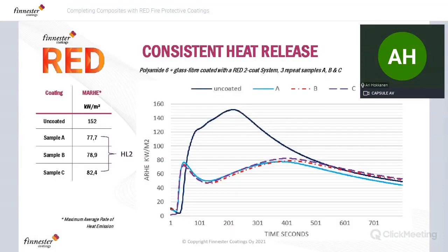And then one further graph we have is what we were talking about, consistency. A big problem particularly in the railway standards world, the EN 45545, is that you have a black and white threshold number that you have to get below to get to a certain classification. In this case, it's called a hazard level. And we're pleased to say that with coatings, you can really get very consistent results. You can get consistent readings. You can see those 3 readings on the left there within 1 or 2 units, kilowatts per square meter. And so coatings basically brings in consistency. You're not reliant on how the composite's been produced. You're not reliant on the slightly difference in the composition or the manufacturing process. The coating fixes it and gives a consistent and reliable heat release result.